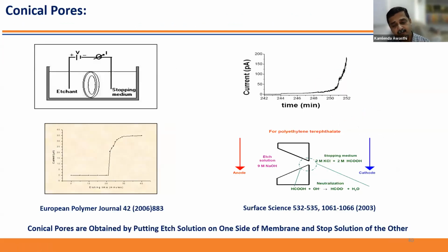So how can we make this cone-like structure, and why are we interested in the cone? If you etch from one side and stop the other side, this is your current and voltage signal. Here you can see it is almost 0. It means both chambers are not connected to each other. Once the current suddenly increases, it means they are connected and you should stop somewhere here. This side is in contact with the etching solution. So of course it is a cone-like structure, and once they are connected, you stop here.